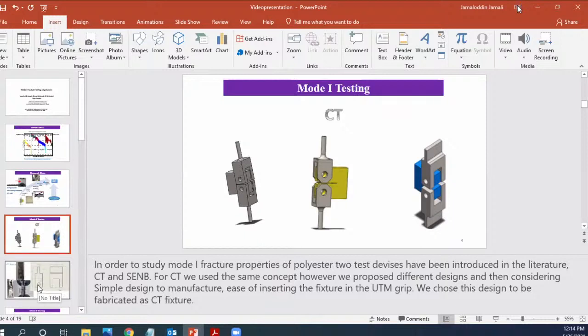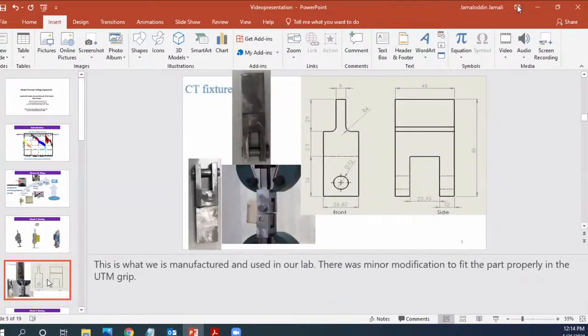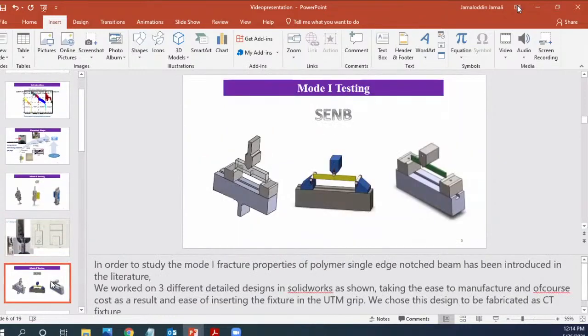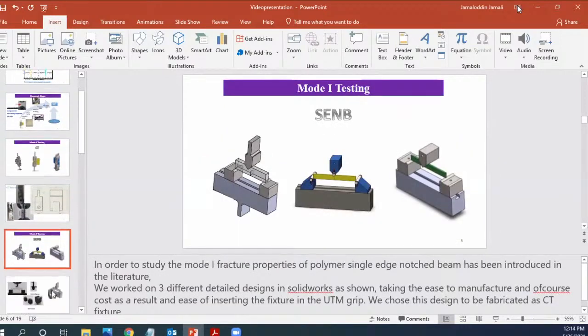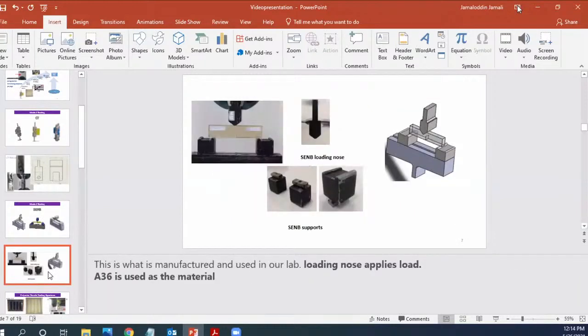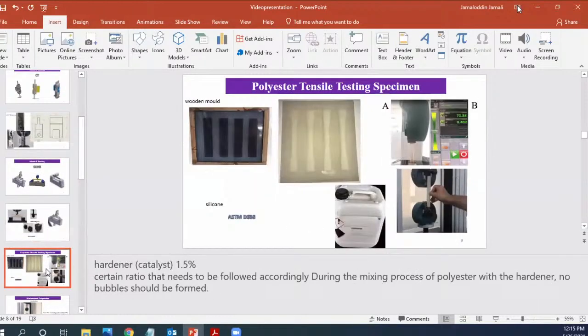So we worked on the SolidWorks design of these models, then went to the manufacturing of CT tests, the same thing for SENB, as you see over here. Manufacturing of CT tests, and also in parallel, we made the specimens. My experience was that using a silicone mold was a good idea. It was flexible, it was working. First of all, we need to know the tensile properties of this specimen, because in order to calculate the strain energy release rate, we need to know some properties such as E.